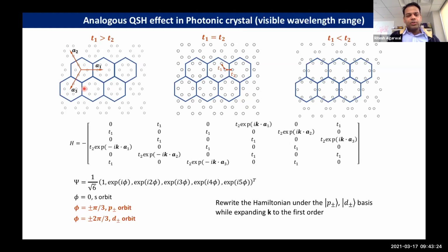So again, once you start with this hexagonal lattice, this is the regular honeycomb structure with a Dirac cone. We can expand the lattice or contract the lattice. If you're aware of the Su-Schrieffer-Heeger model, all this expansion and contracting of the lattice basically leads to different inter- and intra-cell hopping rates. So like in an SSH model, by playing with this intra- and inter-cell hopping, one can create different insulators with different topologies. The idea is pretty much the same, except it has this C6 symmetry. And when you expand or contract the lattice, you break the C3 symmetry of the system, and hence you gap out the system.